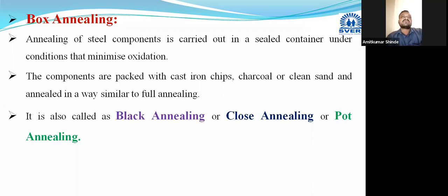How do we seal it? Before starting the treatment process, we take the component and pack it with cast iron chips, some charcoal or clean sand, and after that we conduct the annealing process as discussed earlier.